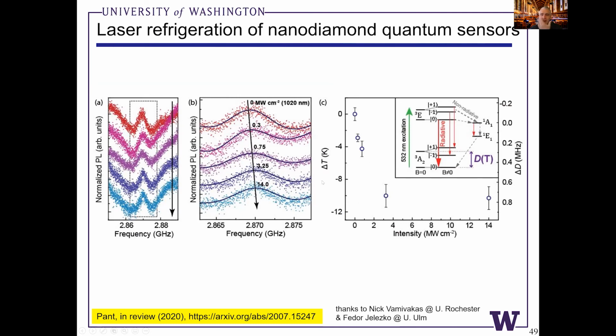And if you want to get a higher brightness, higher intensity for ODMR spectra without photobleaching or darkening your diamonds, or photothermally damaging them, shifting the zero-phonon line of the NV center, this is a way to optically and rapidly compensate for that heating. So I just wanted to share this, our latest and most exciting results at the end of the talk.